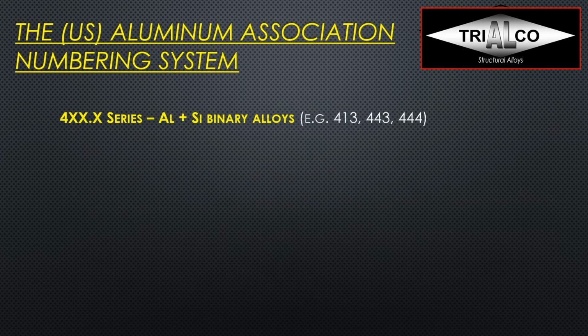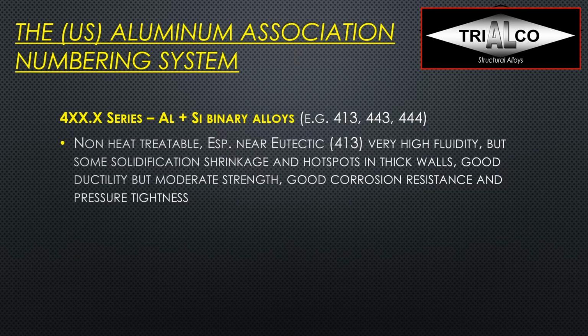So now let's get to the 400 series alloys, and they are a binary alloy. So if we have only two elements in here, so aluminum and silicon, then we're talking about a binary alloy. And most common variants are, of course, the 413. I think most people are familiar with that one, but then there are also 443 and 444. They are non-heat treatable. Well, you could heat treat, but it wouldn't give you anything, because without magnesium, just aluminum and silicon doesn't really do much.